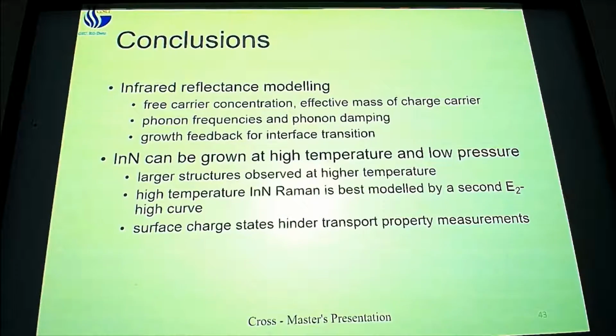Indium nitride, we can grow it at a temperature above the decomposition temperature. At higher temperatures, larger structures are observed, and that might be a clue to getting better indium nitride. High temperature indium nitride Raman is best modeled with two E2 phonon peaks, which gives us better information and leads to a better understanding of the larger structures that appear on the AFM.